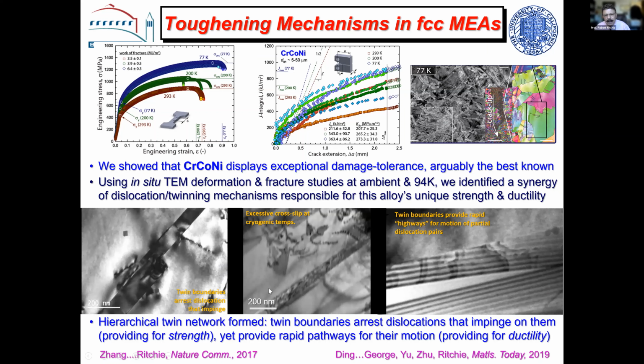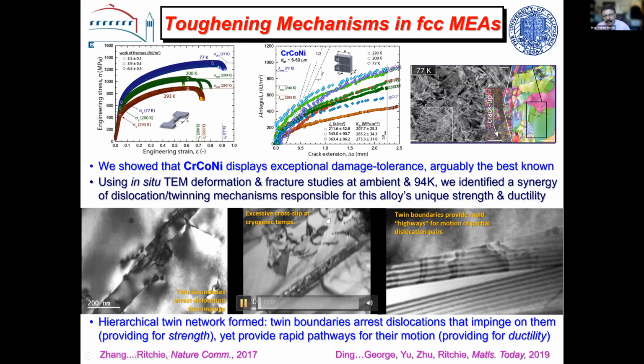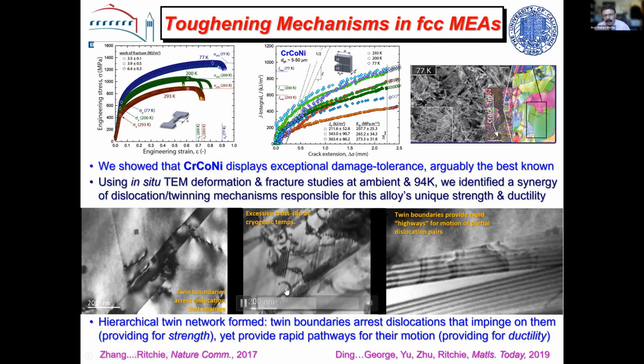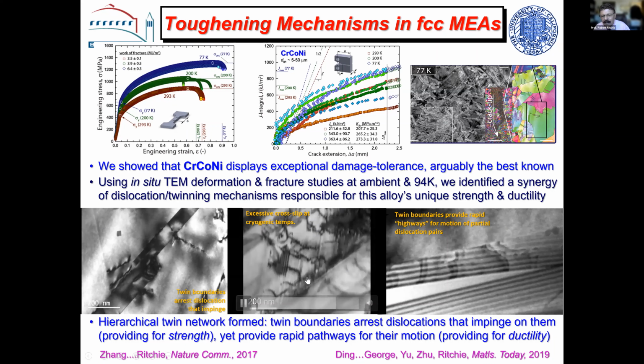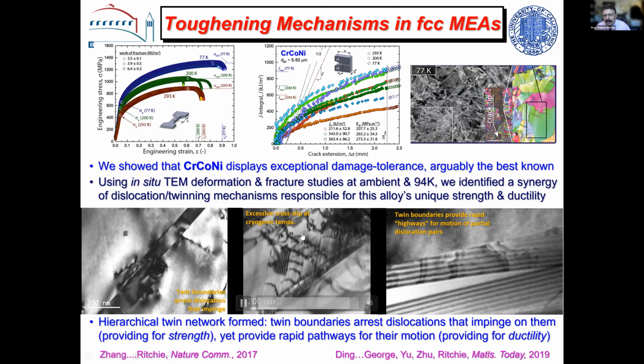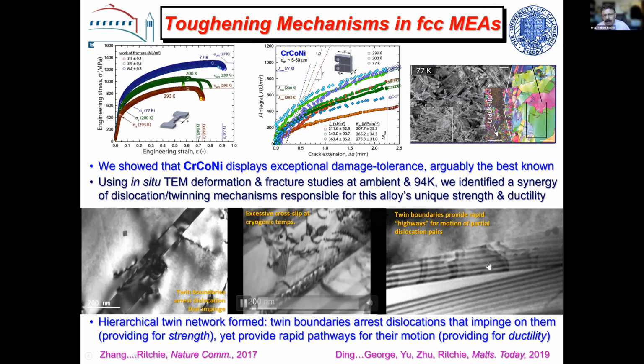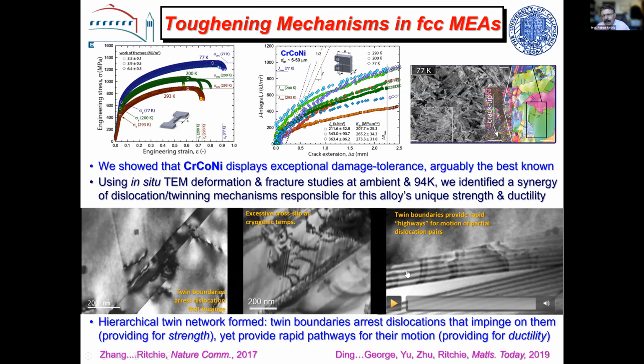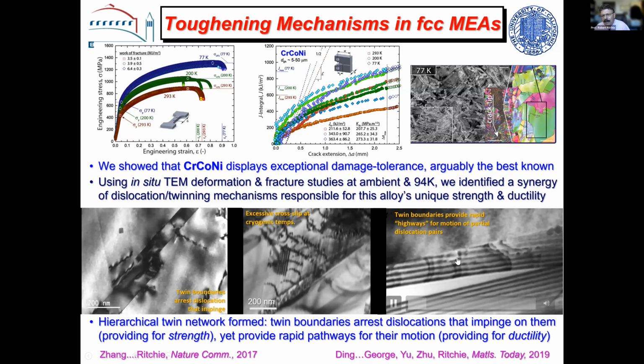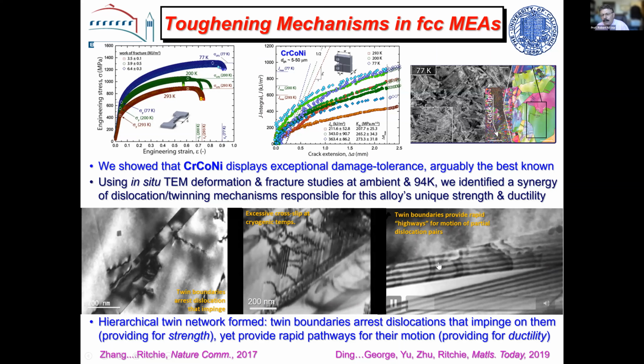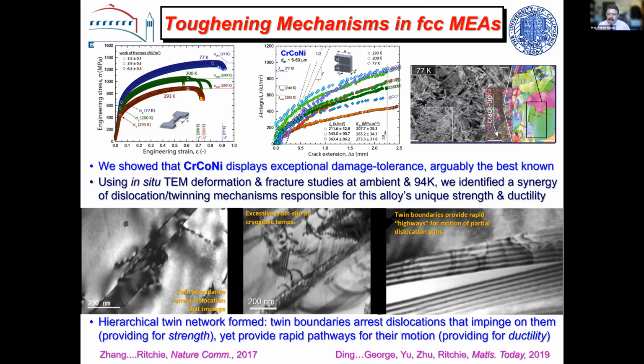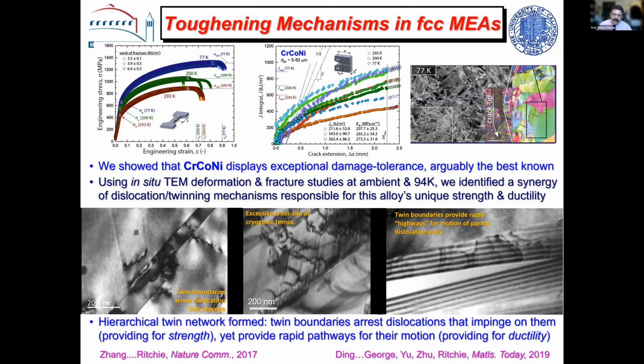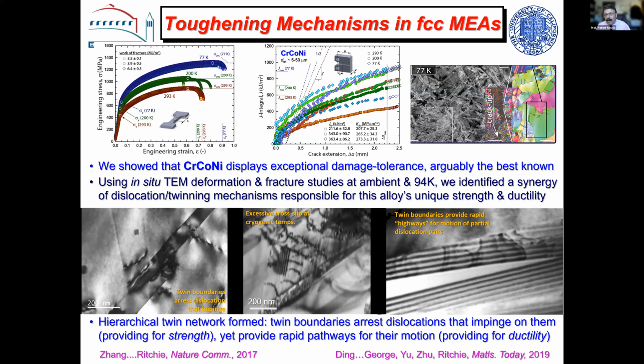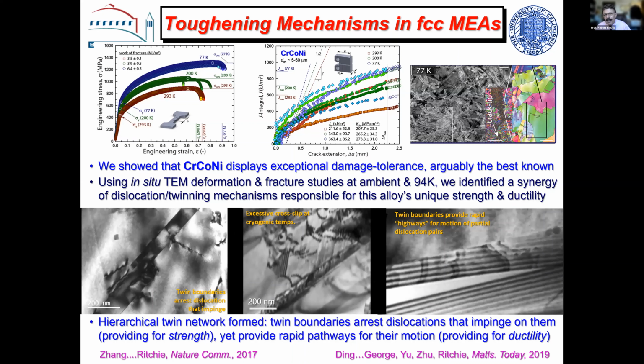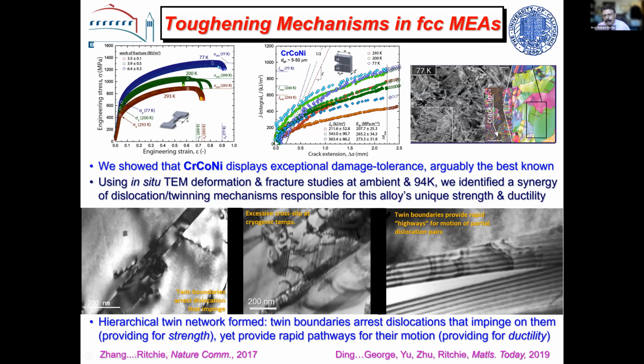We see the same planar slip bands, but if you look very carefully, particularly at low temperatures, you get massive cross slip coming out of those slip bands. So you've got the strengthening mechanisms. This is a ductility mechanism due to the cross slip. And the other thing that's intriguing is the twin boundaries themselves act as highways for the partial dislocations to move on. You can see the dislocations are moving along that twin boundary. So we again have a duality of mechanisms that promote ductility and promote strength. And of course, this generates strain hardening, which is the key to their very high toughness.